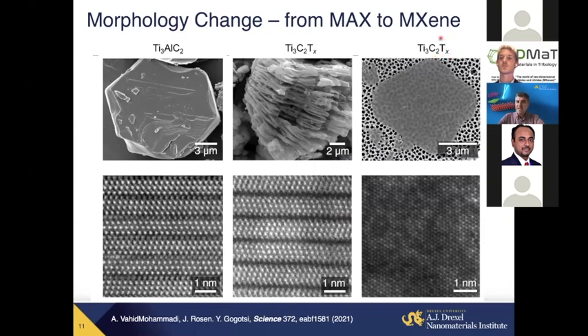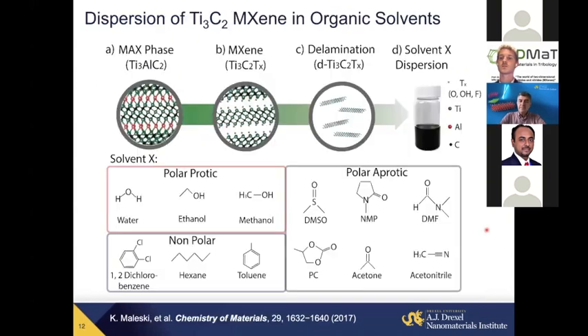TX stands again for surface termination here. And you can see it's electronically transparent. It's just about 1 nanometer in thickness. And you can also see a well-ordered crystalline structure. So they remain strongly crystalline materials.